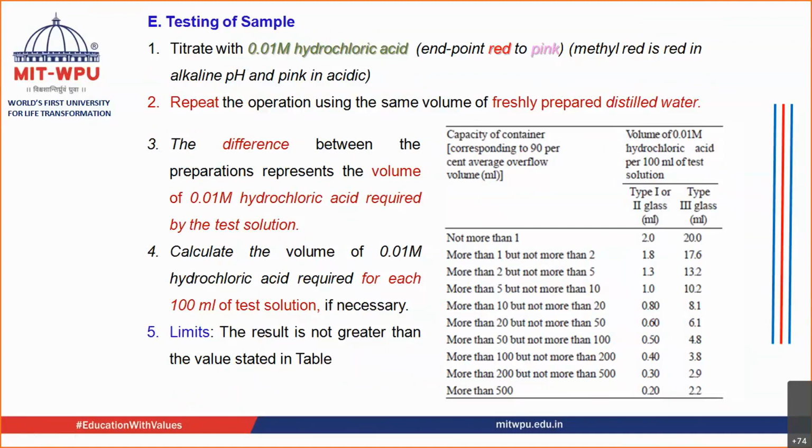It has come inside the distilled water. Okay, when you're carrying out the autoclaving, etc., which you have now collected, it contains alkali in which you have added methyl red, and now you are going to titrate it with 0.01 molar hydrochloric acid. If you remember, yesterday when we carried out the test as per USP, the powdered glass test, we